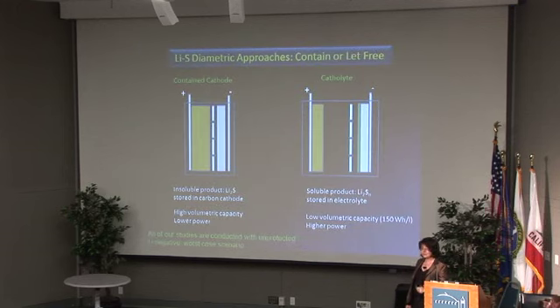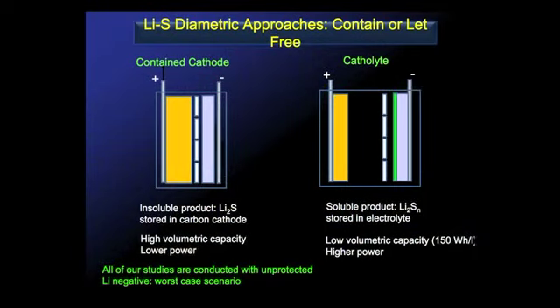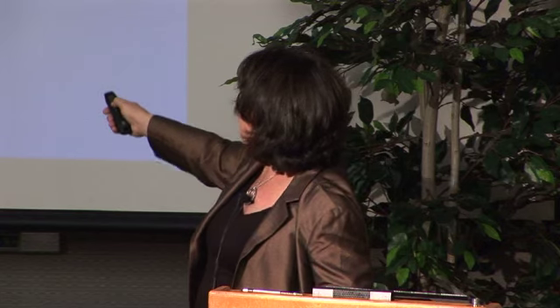So there are two approaches to sulfur batteries, and one of them is what most people call a catholyte cell. That's where you just operate in that limited regime of the soluble polysulfides, typically speaking. These ultimately would deposit on the metallic lithium negative electrode and cause all sorts of problems with insoluble products. So such cells have to have a protective coating, which is an ion conductive glass. That insulates those polysulfides from reduction, and therefore they do not reduce to form the insoluble precipitates, and the cell can carry on. So these are absolutely required.